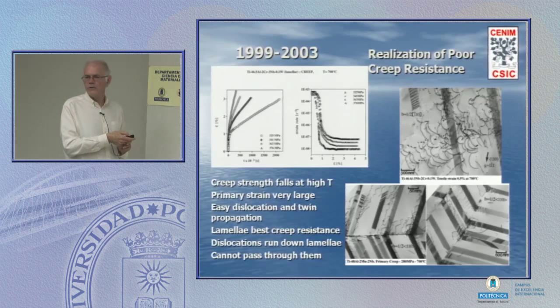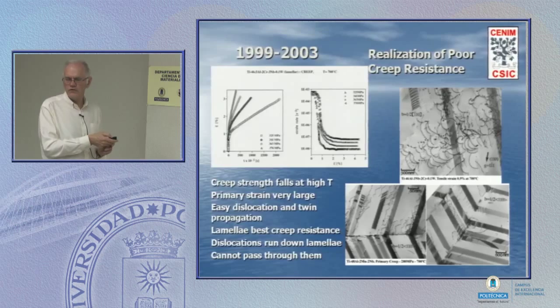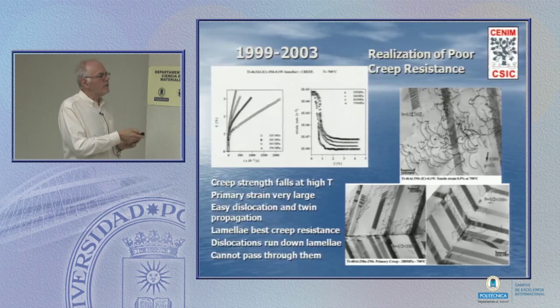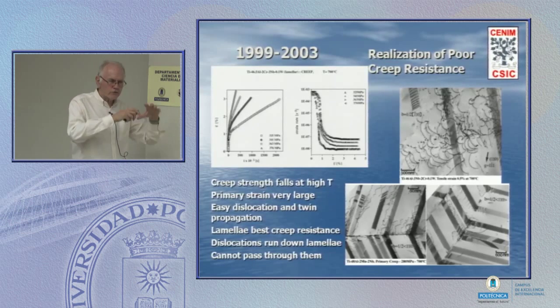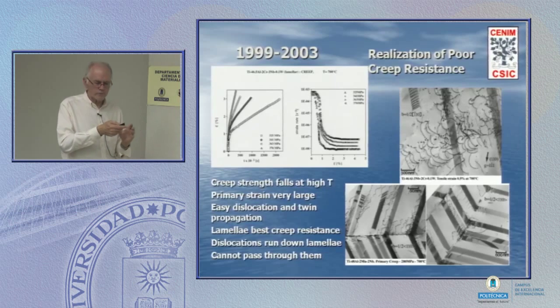The reason it happens is that within a given phase, it's very easy to emit twin dislocations or emit normal dislocations. And it's only when these interact that you have a sort of work hardening that the creep rate becomes very, very low. Until then, it's a very soft grain. It's a very soft material.